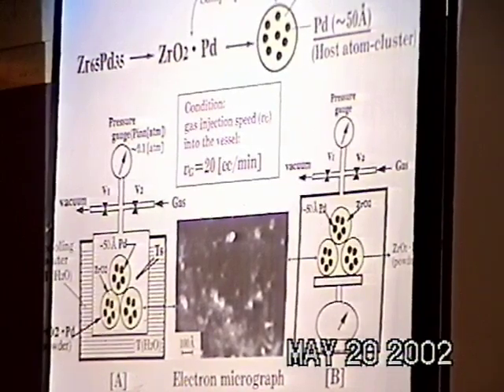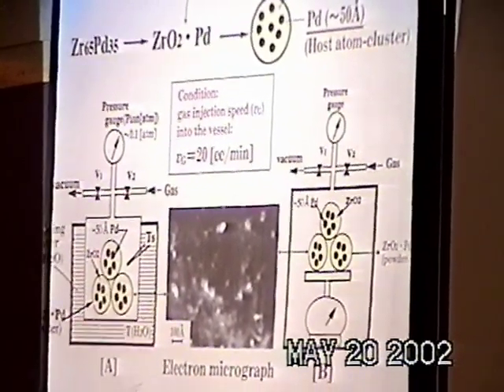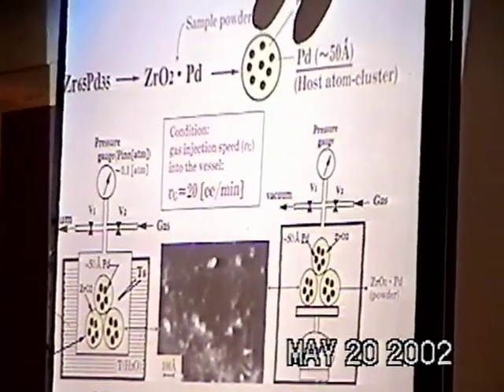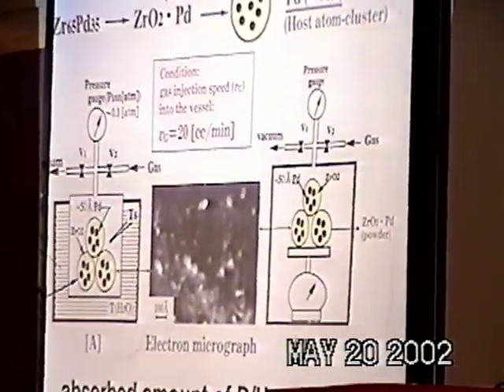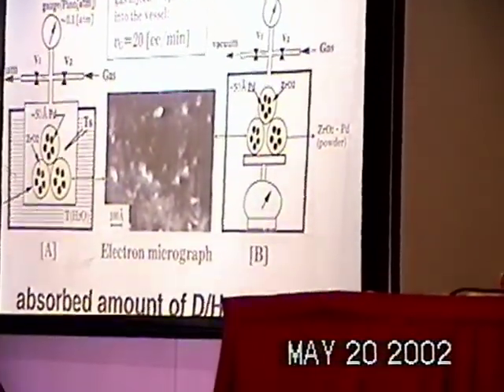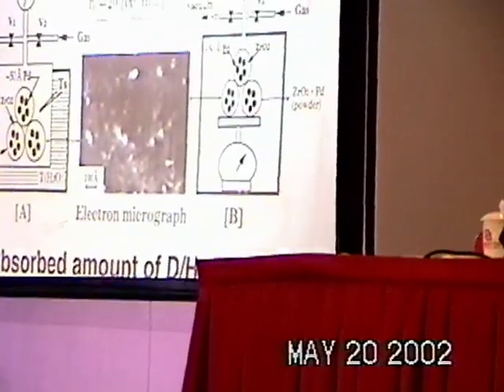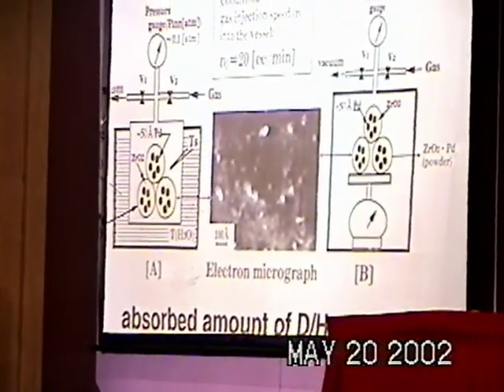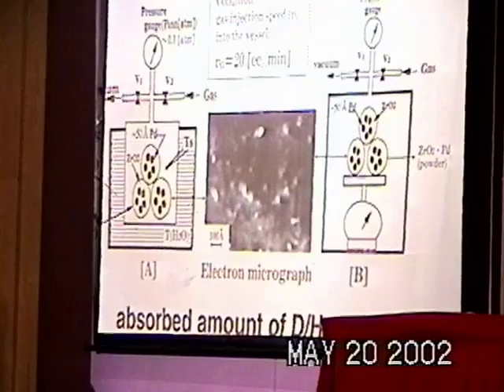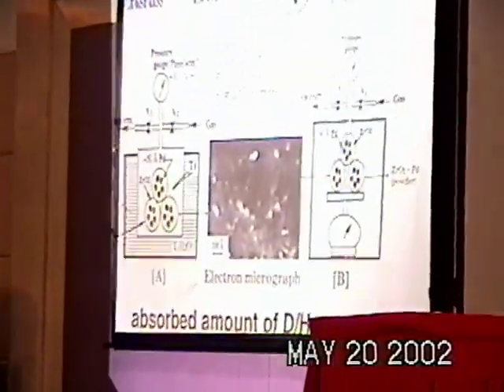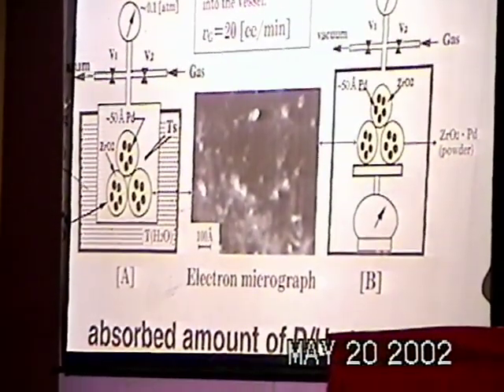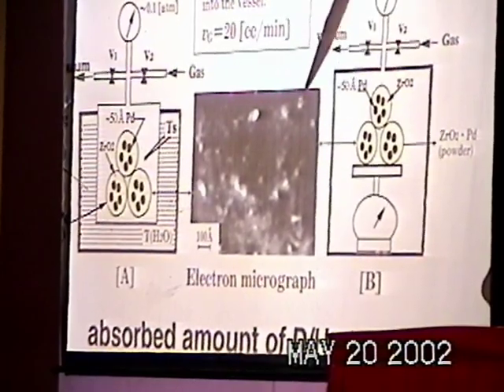First, amorphous Zr65Pd35 was prepared and heated in air so that the zirconium was oxidized. As a result, palladium clusters of size about 50 angstrom were embedded within ZrO2 matrix. Middle zone electron micrograph shows palladium clusters. Next slide.